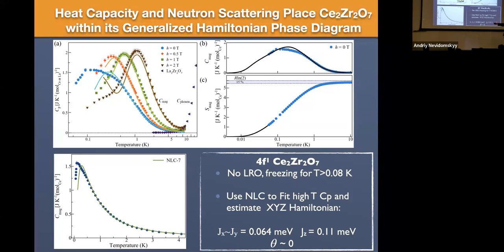We get together with our theory friends, in this case at Dresden, and they perform this calculation, which is referred to as a numerical link cluster calculation. It's an exact calculation on a finite size lattice, and the finite size lattice in this case is 7 tetrahedra. That's as good as they can do. It works kind of like a high temperature series expansion, in that it will give you accurate results so long as the correlation length in the real system is shorter than the system size you're doing the calculation on. So it's shorter than 7 tetrahedra.